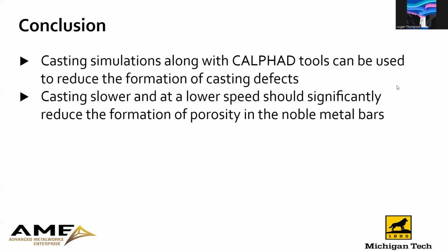So in conclusion, casting simulations along with CALPHAD, that was ThermoCalc, tools can be used to reduce the formation of casting defects. And casting slower and at lower temperatures should significantly reduce the formation of porosity in the noble metal bars.